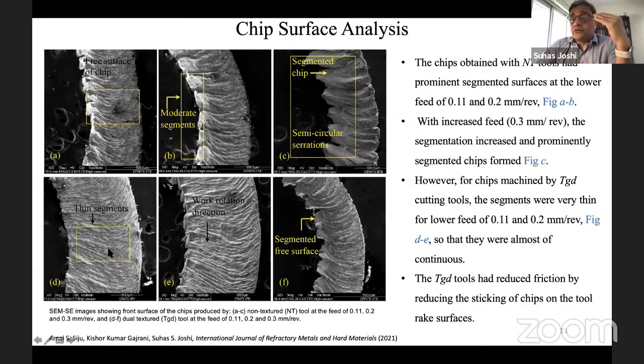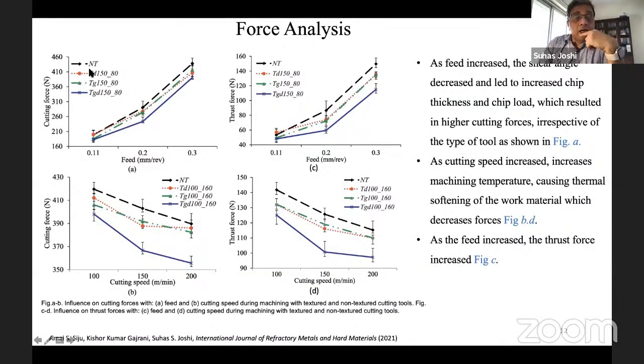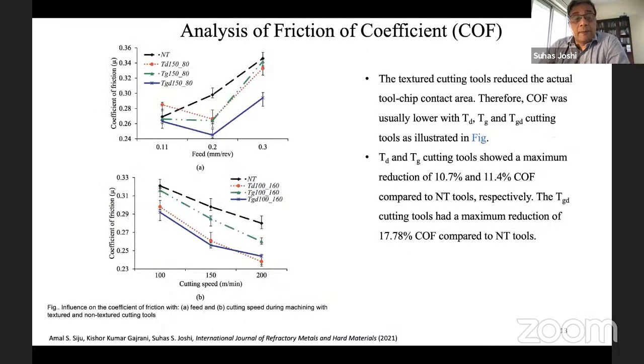But when you use the textured kind of tools, these examples of dual textured tools, you will find that even at higher feeds, the segmentation has significantly smoothened because of the textures. Among all kinds of textures, the first line always corresponds to the non-textured tools, whereas the last line corresponds to the dual textured tools. And you can find that in all the cases, forces etc., there is a significant reduction of the order of 17 to 31% in the cutting forces. Coefficient of friction also reduces significantly when you are using these kinds of dual textured tools.